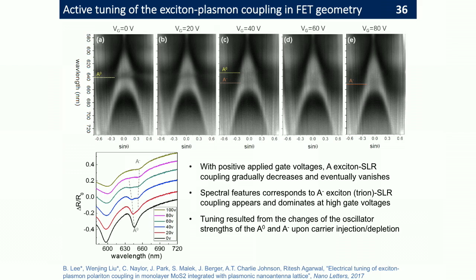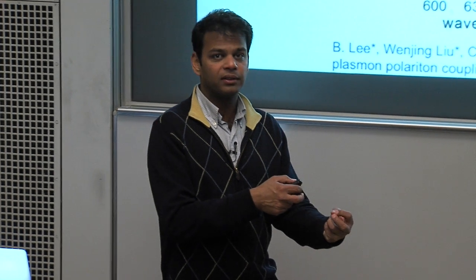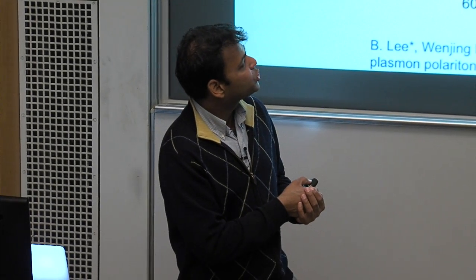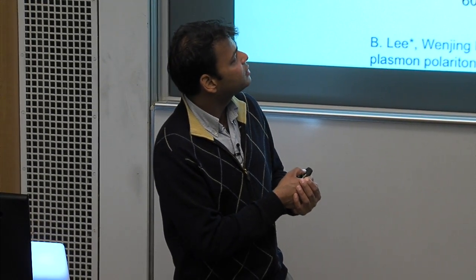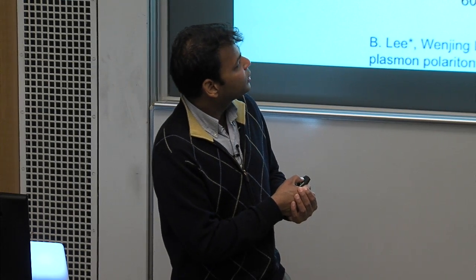And then as we start to apply gate bias, which basically means we're injecting more and more carriers into the system, then something very interesting happens. At some intermediate regime, we start seeing two polaritons form. One very strong with the free exciton that we started with, although it is becoming weaker compared to where we started from. But another polariton type branch starts to emerge, and this now matches the trion excitation, which is an exciton and an extra electron. So which basically means now we can get strong coupling at this intermediate injection limit with both the free exciton and this charged exciton or trion.